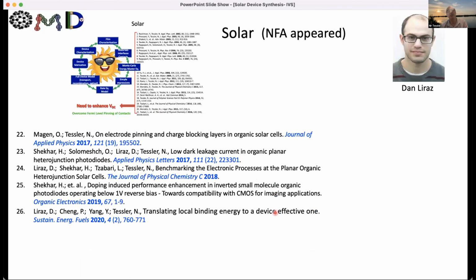And then P3HT:PCBM was gone, and we have the non-fullerene acceptors. And it seemed that we had this magic material, then the open circuit voltage is not a problem anymore. And then Dan started to look carefully into the physical mechanism. And we see that charge separation and extraction becomes an issue.